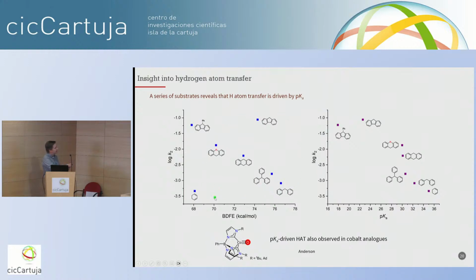I guess you could exclude this one and this one. You could imagine it's a straight line, but the data points are sort of all over the place. However, if you looked at the pKa of those C-H bonds, then there's a much better correlation. So it appears that the mechanism of hydrogen atom transfer is driven by proton transfer. And that's very much like what John Anderson saw from the cobalt oxo complex.